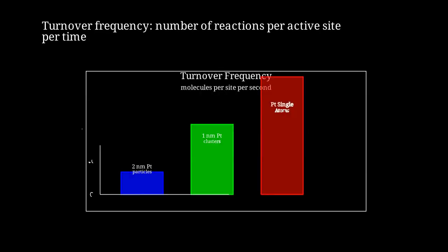Look at this bar chart. 2 nanometer platinum nanoparticles show a turnover frequency around 10. 1 nanometer clusters show about 30. But platinum single atoms show over 150 molecules per site per second. That's a 15-fold enhancement over traditional nanoparticles.